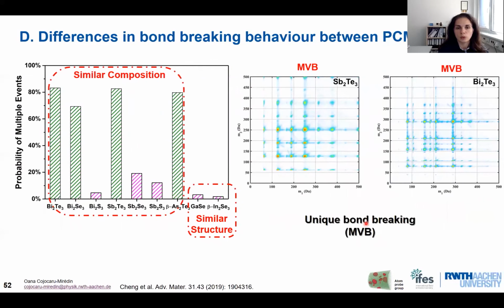Also, if we take compounds which have a similar composition, like antimony telluride and antimony sulfide, but have different structure and different bonding mechanisms, we see that having a similar composition doesn't mean similar behavior in terms of bond breaking inside the atom probe. We see typically that the materials which have the unconventional properties show a very large probability of multiple events, although the other covalent or ionic materials show a pretty low probability of multiple events.